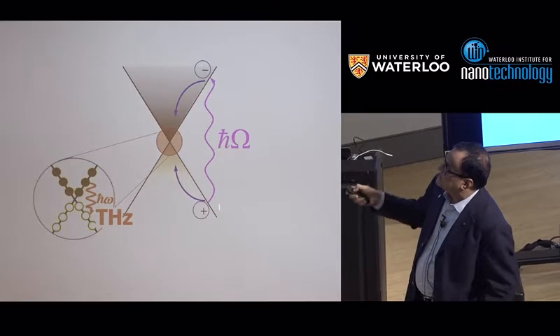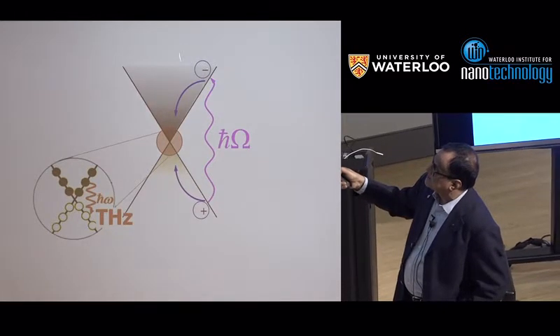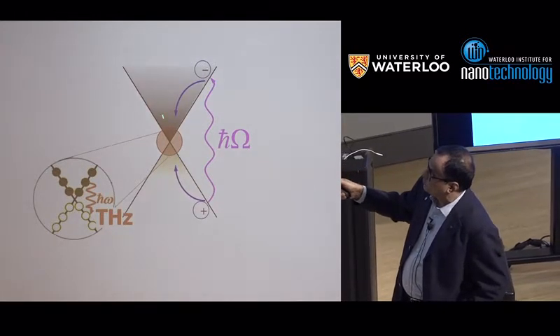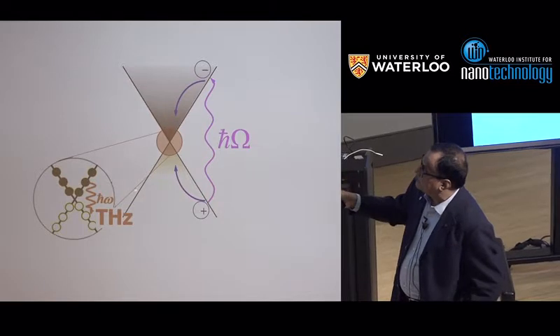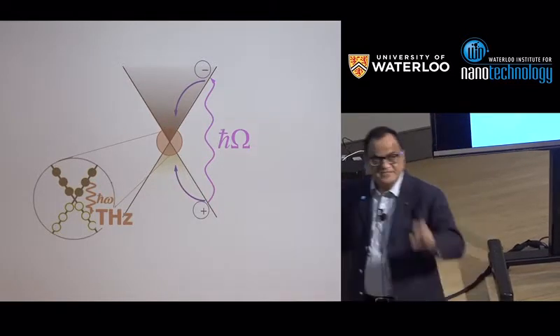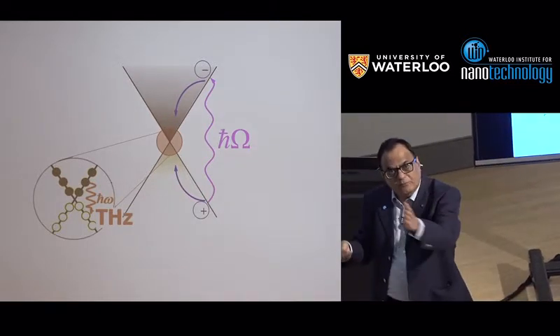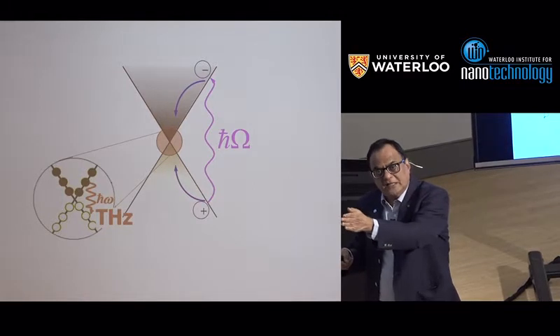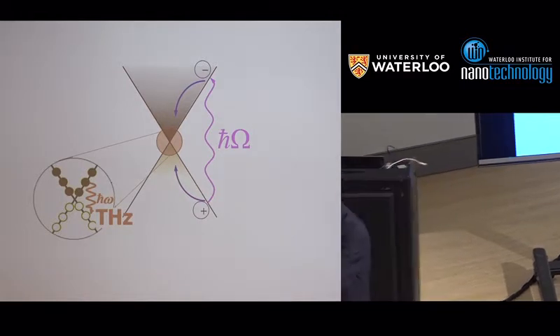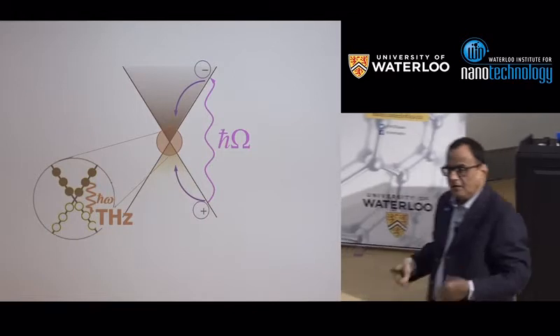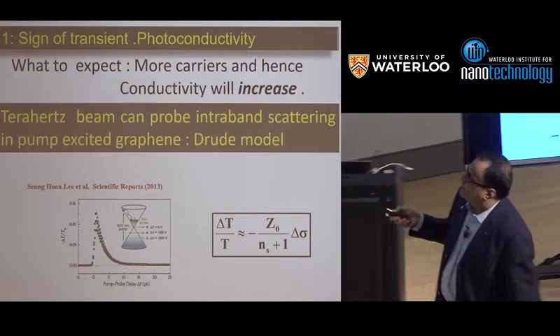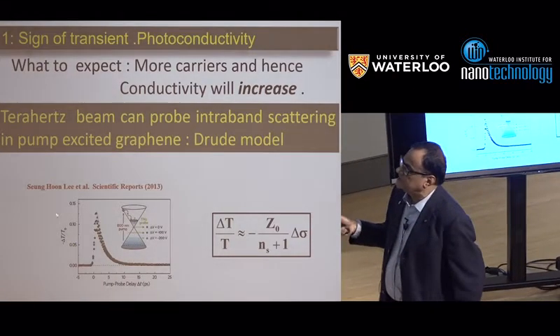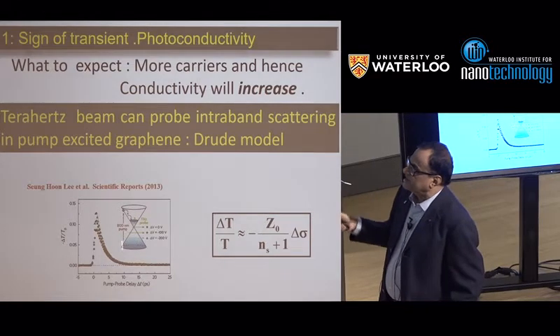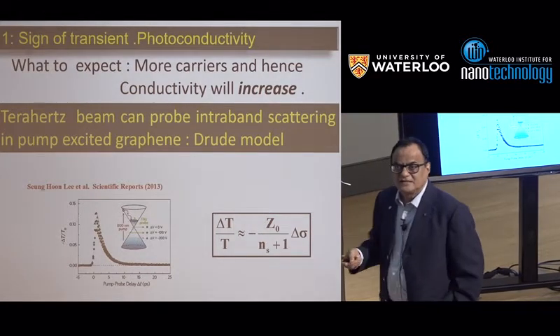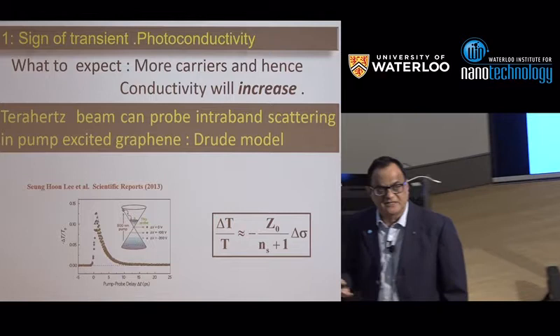You put in a visible laser, all these carriers relax. This is what we want to probe. And at that time, you put in terahertz radiation as a probe and vary the probe time with respect to the pump pulse and ask what happens to carriers as a function of time. And this is something we explore. The first thing is you measure terahertz conductivity as a function of delay time. This is the first obvious thing to do.